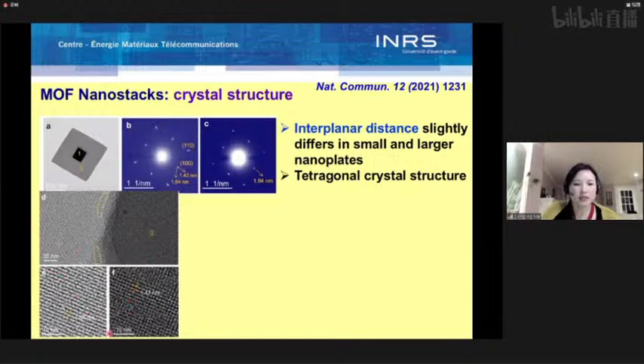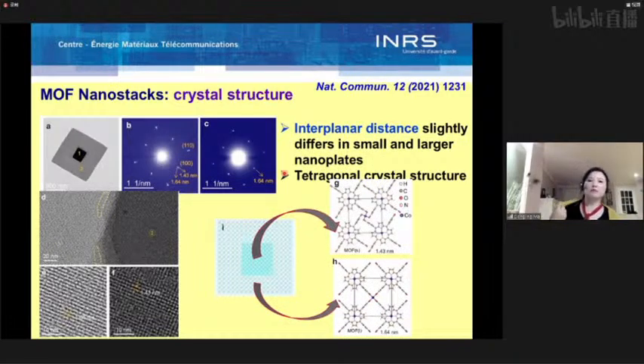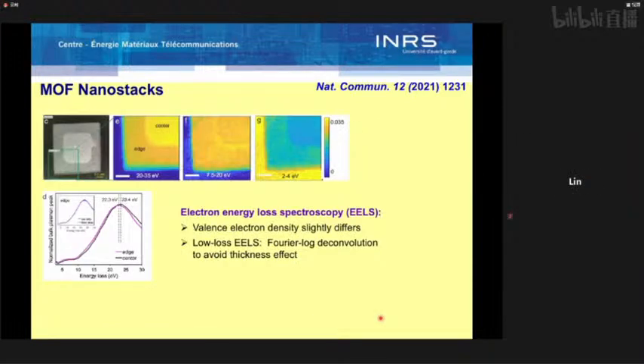We observe a similar thing by high resolution TEM. Here is the center part, here is the edge part, and we observe slightly different lattice fringes. So we think that the interplanar distance of the top and bottom nanoplates differs slightly, but both have a tetragonal crystal structure. We did more experimental work and also theoretical calculations and finally identified the structure. The top plate has a lattice constant of 1.43, and the bottom plate has a slightly larger lattice constant of 1.84.